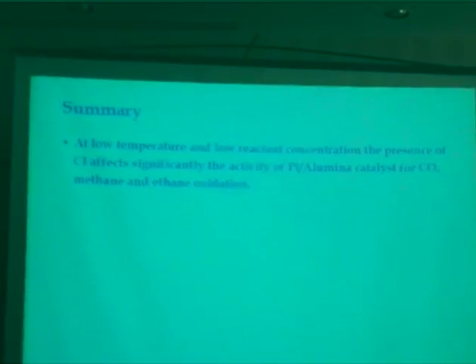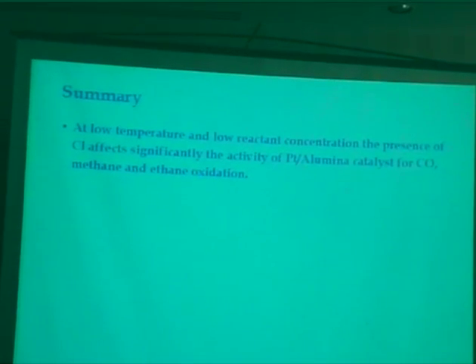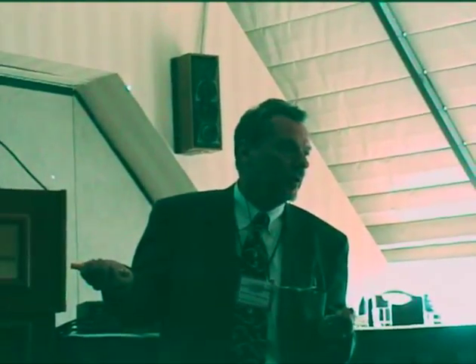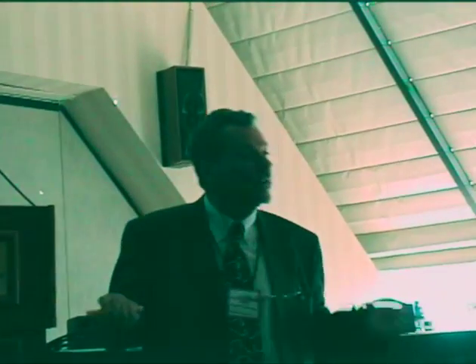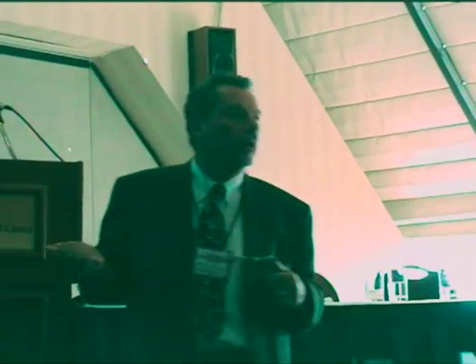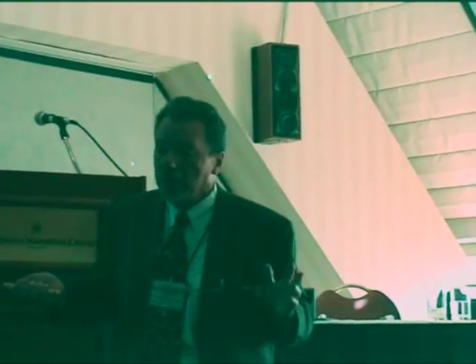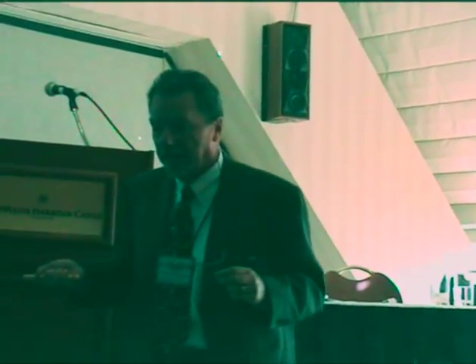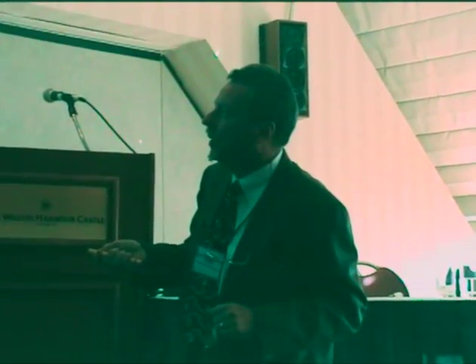you will tell me, oh, it doesn't matter. No, it does matter. On silica, the temperature shift is about 50 centigrade. All right? But when you reduce it, it's fairly easy to get rid of the chlorine on silica because it doesn't stick to the support, the silica support, as much as the alumina support. Okay? So when you oxidize again, then it looks like you have your chlorine-free catalyst again. So this is sort of the gist of the story here.